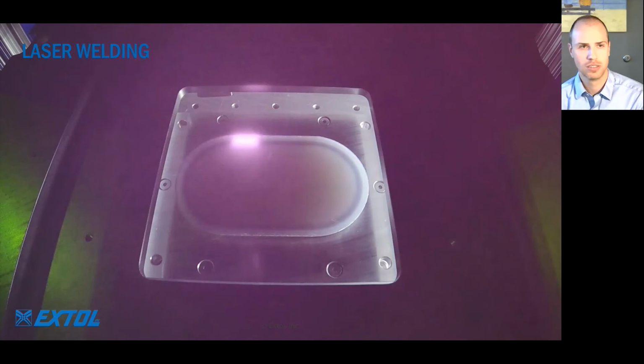Jason, I saw a question. Is it possible to use PA nylon in both parts, the transparent without CB? I'm not sure what CB. Without carbon black. Carbon black, thank you. Yes, PA12 will also weld to PA12, that's printed outside of 3D printing. There are even two parts that look black that may be able to be welded together if the top part is specially engineered with material additives to allow the transparency to the laser wavelength to pass through it. So a lot going on there, but yes, certainly possible.